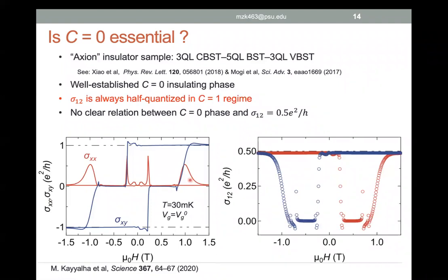And then I made niobium contacts on top of them and measured the two terminal conductance across these samples as well. And then I saw that the conductance, regardless of whether you have this insulating Chern insulator 0 or not, is always half quantized. So that really does not play any role in this half quantized